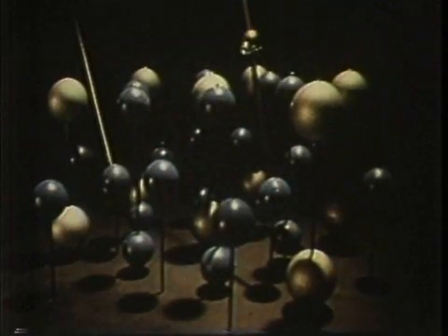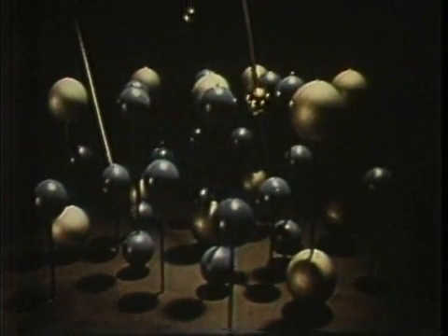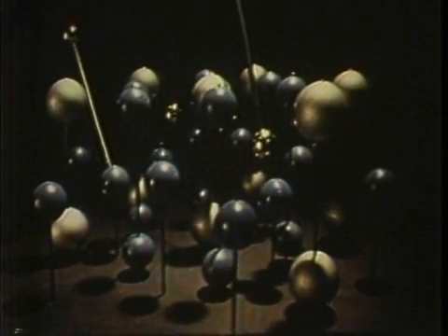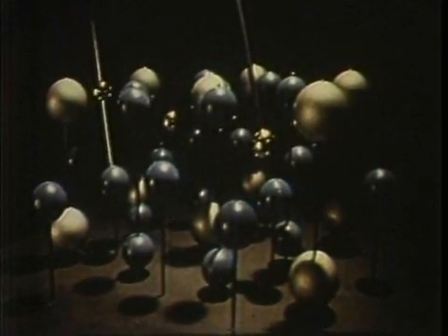The hydrogen enters through these cracks, goes down to finer and finer cracks, and finally ends up actually located between the atoms, right in the atomic structure of the metal itself. So in summary, what we have here is a solid metal sponge for hydrogen gas — a very safe and compact way of storing hydrogen in a solid form.